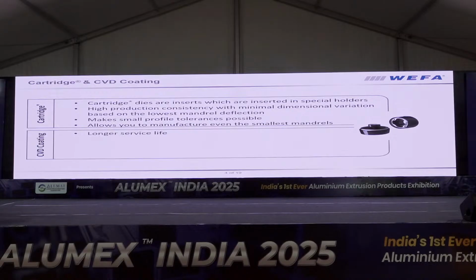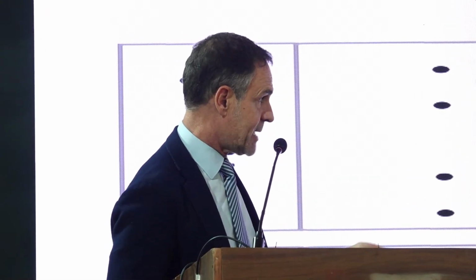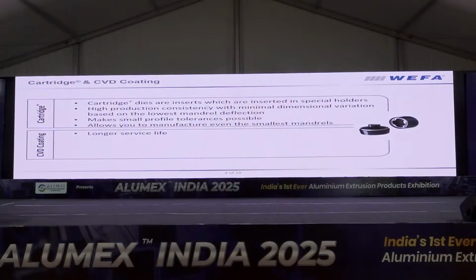And then what does the CVD coating do? CVD stands for chemical vapor deposition. It's a special treatment of the die after production. Instead of nitriding, which would mean renitriding 5, 6, 7 times, we would just do one single CVD coating. All the coating materials are evaporized, and on the hot tool surface they build up layer by layer into a very hard coating of almost 2,000 or 3,000 Vickers.